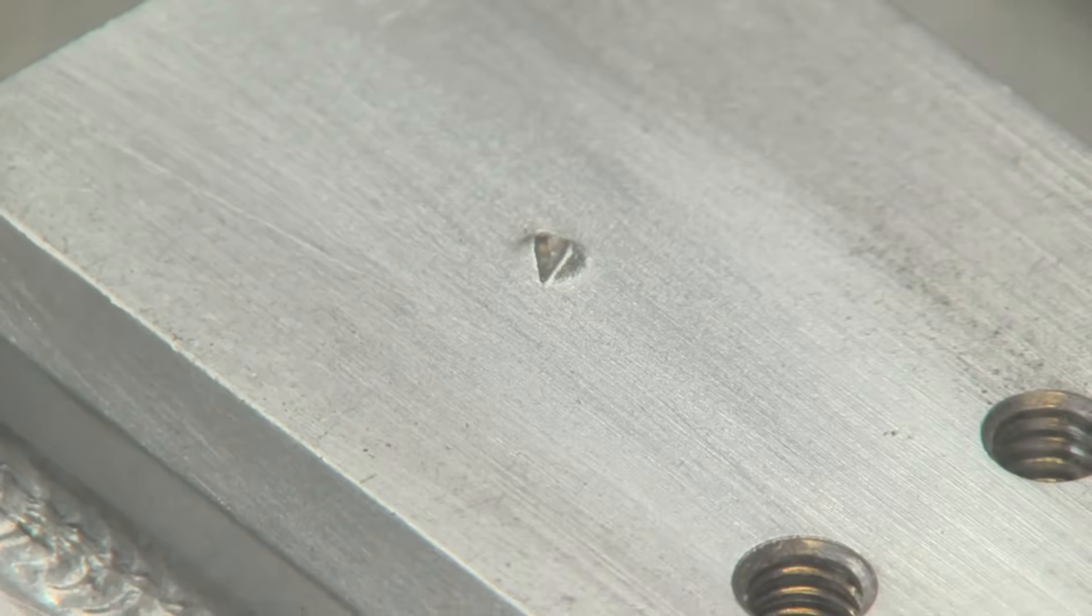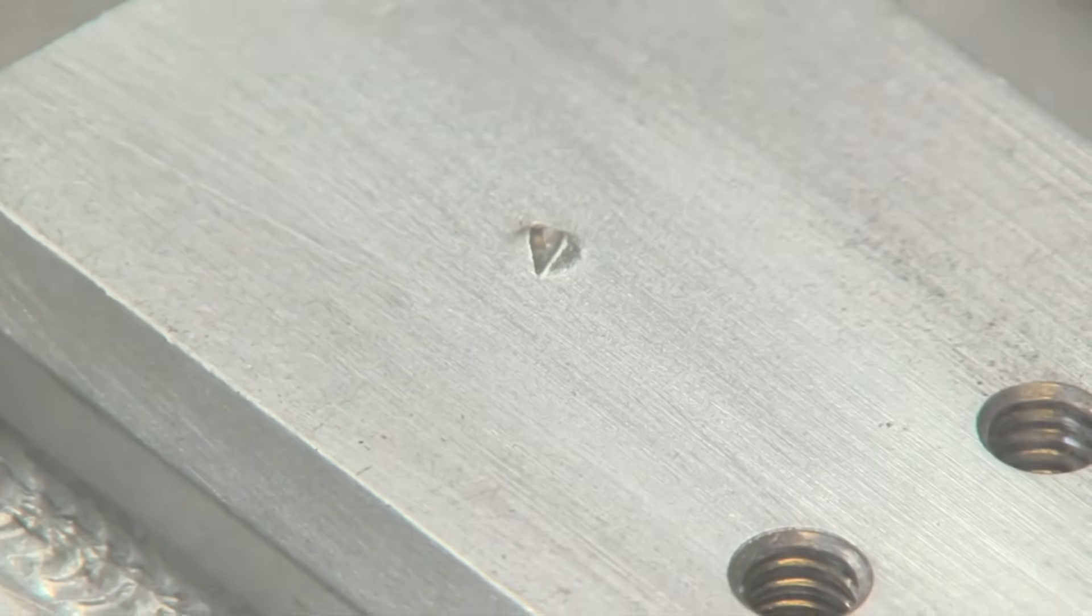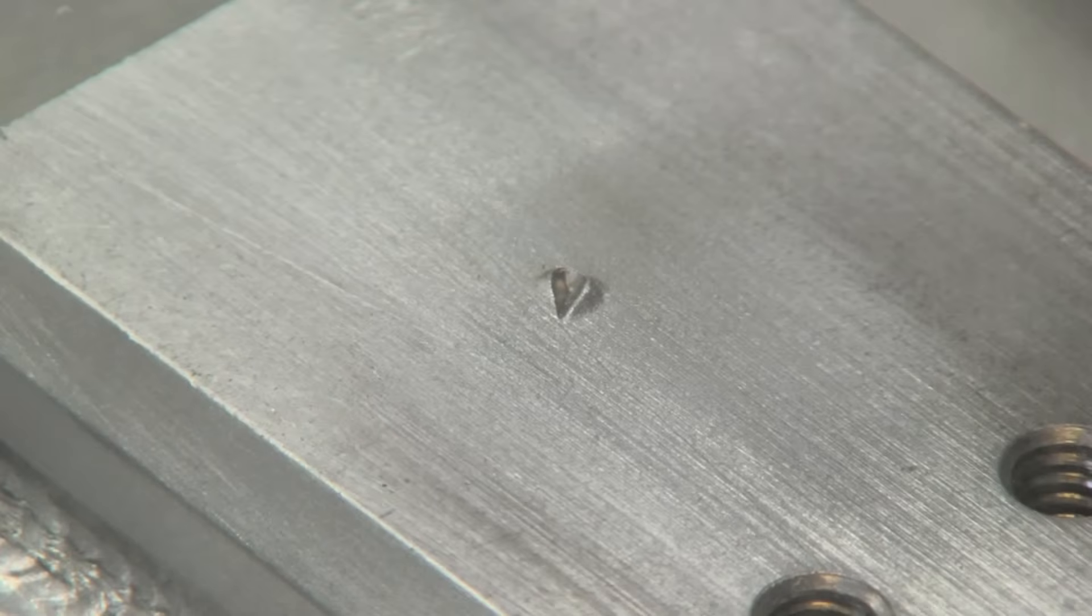Another great example of DC application is a pit, a ding, or in a mold of some kind. This is done intentionally with a corner of a chisel, but just you can puddle the thing like that almost immediately. And just that one little dab of filler wire, no preheat, no pitting from the AC action, or anything like that, and you get nice deep penetration and it cleans off really nicely, and you don't affect the temper of the aluminum nearly as much.